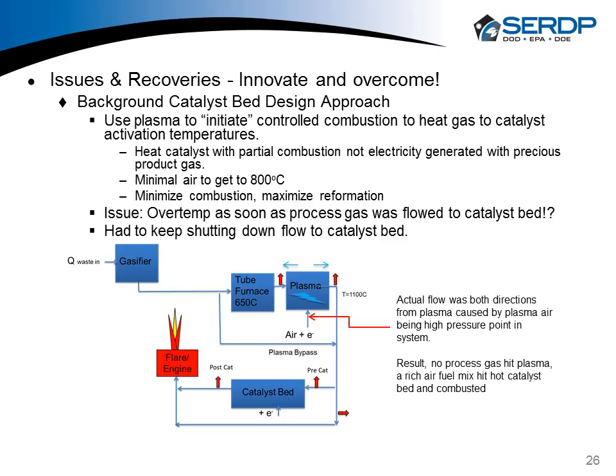And we played around with it, and eventually later on we figured out that, again, we're injecting air into the plasma, and it was flowing in both directions, giving us an air-fuel mix that when it hit the catalyst bed at the 800C, apparently it was enough to initiate combustion, or maybe it was even combusting in this line. Again, we were blind with respect to the temperature. We wanted to be around 1100, but we couldn't really tell what was going on. Not until we got into the catalyst bed and had thermocouples there, we could see that we're getting hot faster than we should.